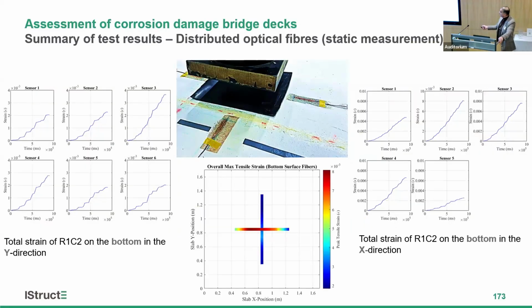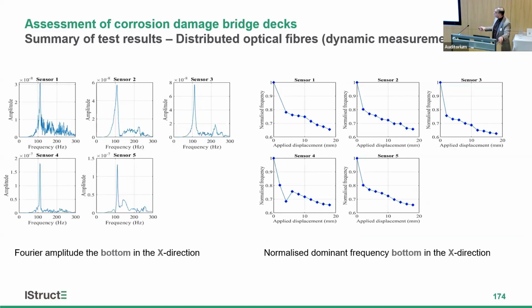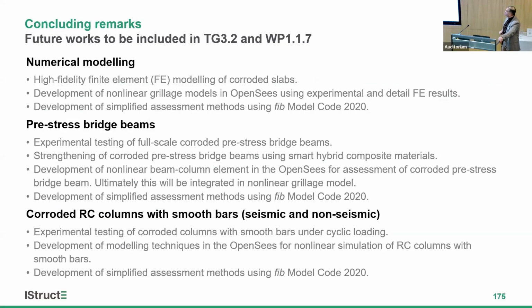So the fiber optic also shows that we can detect it under the top and bottom, and this was the static. And these fiber optics are able to get the dynamic measurement. So the bandwidth of these optical fibers is 500 kilohertz. So we can essentially detect any small crack. And this is essentially a hammer test. We did the time history of the data, and then we did the FFT, and we could actually see the frequency change, which is essentially related to stiffness, and can be used for health monitoring in the future.